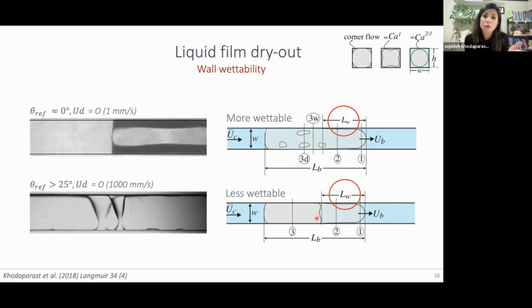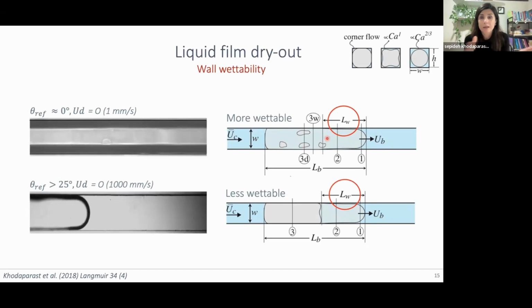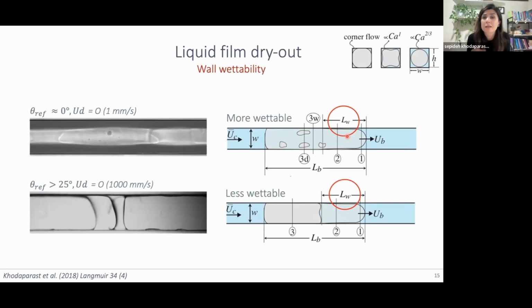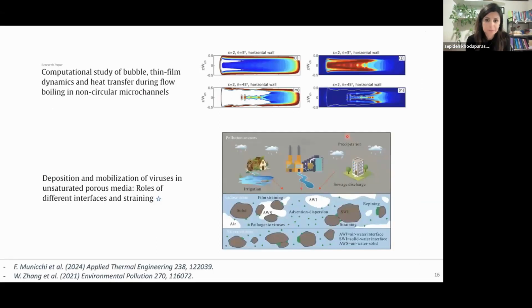But the moment you lose this thin film, you start having these hot zones around the bubble, and that's what you want to avoid. So the idea was that if we have a good prediction model for this wetted film at the front of the bubble, maybe we can help some applications at least. And the scenario when you go to oil extraction or hydrology is way more complicated.